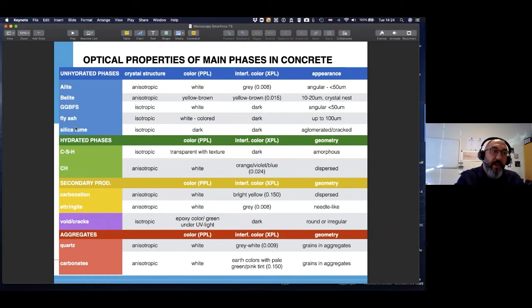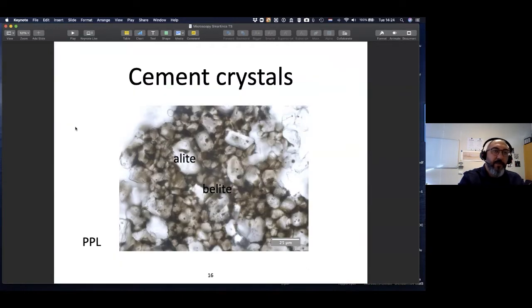The unhydrated phases, hydrated phases, maybe there will be secondary products like carbonation and ettringite. There will be, of course, porosity, voids and cracks, capillary porosities, and aggregates. What kind of aggregate are you using? Quartz-based, carbonate-based? All these things can easily be characterized with these optical microscopy techniques. So let me give you some examples.